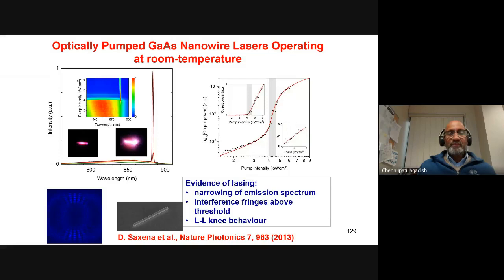And you also see the interference fringes showing that these are going to laser, a coherent light emission is coming out. And you can also see that Drew Saxena has simulated one with the measured devices, and they're very much comparable with the simulations, the interference fringes he's measuring here also. Here is the output versus pump intensity, again threshold-like behavior. The log-log plot showing the S-type behavior. This part is the spontaneous emission, this part is the amplified spontaneous emission, and this part is the one where you end up getting the lasing taking place here, for example.